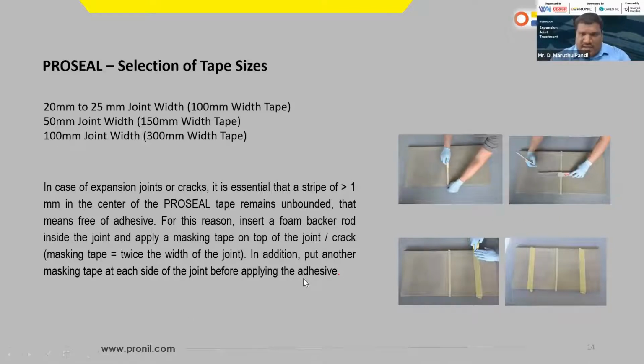I just want to explain, just imagine an expansion joint of 20 mm or 25 mm. The selection of tapes is very important. The tape has to be selected at twice the width of the joint. That is mandatory. So if it is a 20 or 25 mm joint, a 100 mm tape has to be selected, or for a 50 mm joint, a 150 mm tape should be selected. So here is a small application process which shows how to apply ProSeal.